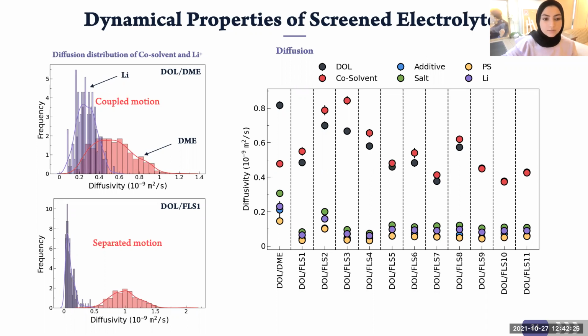Whereas in the fluorinated solvent system that has around 70% degree of fluorination of the solvent, you can see that there is almost a separated motion because this type of solvent is not participating in solvating the cation.